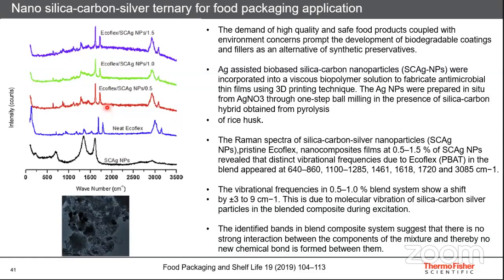So this is how Raman spectroscopy can be used to understand the interaction of materials with the system. However, there is no strong interaction, or no new peak that appeared when you do this Raman analysis of different concentrations of samples, which indicates that no new chemical bond is formed. Rather, it's just an interaction, or blend, or incorporation of the nanoparticles in the material during the formation of this film. For details, you can go through the references mentioned at the bottom of this slide.